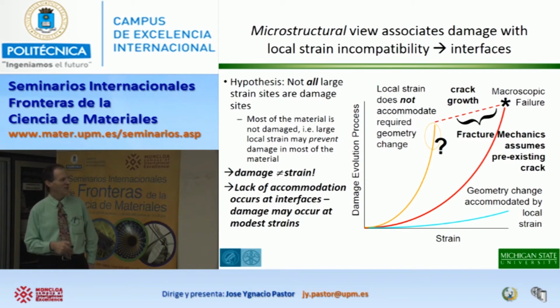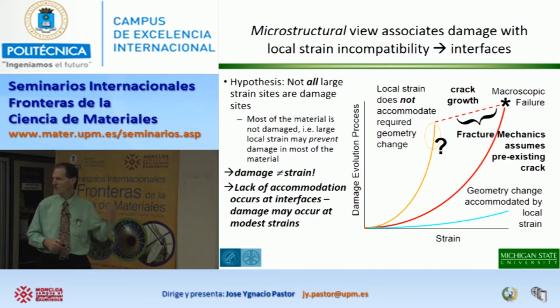If I think about the vertical axis being the damage evolution process, I can imagine a portion of my material that strains an awful lot. And if that strain accommodates a necessary change in geometry, I don't generate much damage. On the other hand, if I have in the same material a region where it is not deforming so much, but it does not change its shape properly to accommodate the required shape change, then maybe we might get some damage. So in a sense, ironically, we might have the opposite condition of what I just showed. A smaller strain region may actually be a place where damage begins, and maybe nucleates a crack, and then that crack grows to the point where it becomes a macroscopic failure.